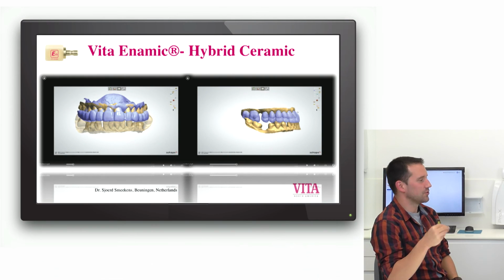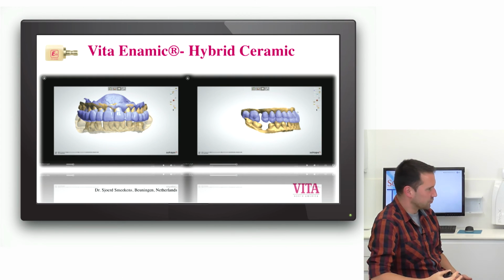Why was it so important to use a hybrid ceramic here? We have enough room, we can do zirconia or ceramic or whatsoever, but in a dangerous occlusion like this, I don't take any chances. I don't want my ceramic to chip. I want the material again that is a natural flexural shock breaker and that can be repaired if things go wrong. But also much more important, we don't prep. So our outlines finish to 0. I don't know any ceramic that can be milled to 0, even if you would press it. So that's why it was so important for us to use a hybrid ceramic, because we can finish those outlines to nothing, so that you don't feel any limit.